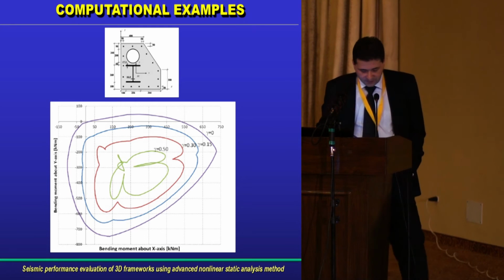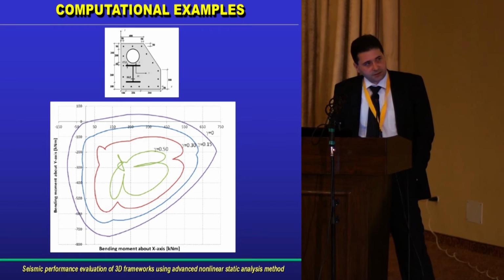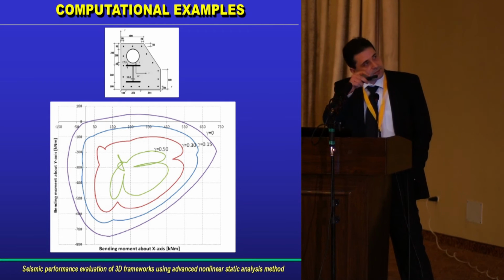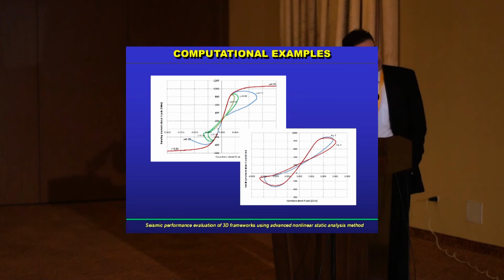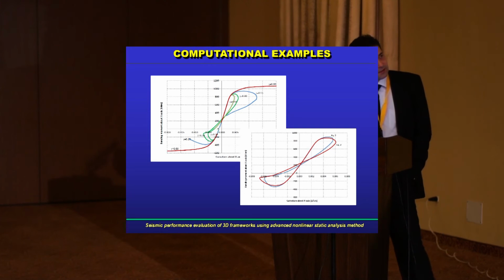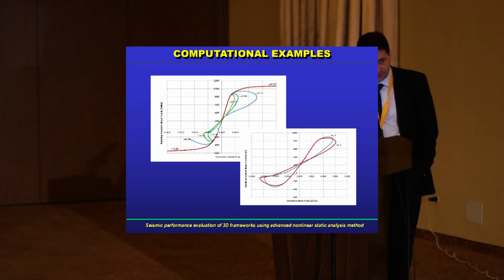Another interesting result: when considering the residual stresses throughout the encased steel profile in composite steel cross sections, the residual stresses reduce the ultimate strain capacity. For instance, these cross-sections are analyzed considering different levels of the compressive axial force and different distributions for the residual stresses, using European distribution and American distribution. And we can see that the ultimate strain capacity is reduced with increasing the axial force, and this reduction reaches even 40%. So the consideration of the residual stresses for the encased steel cross-sections is important to take into account.